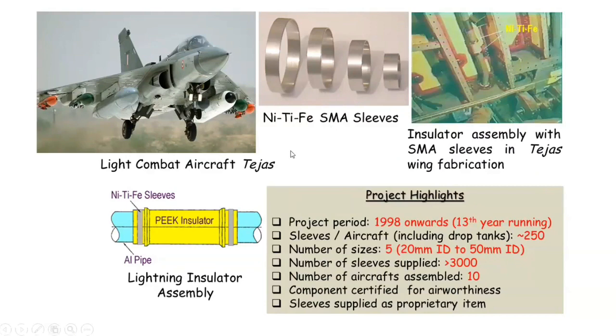So what is done here is that the service window for this application is between -50 and +150 degrees. So this material, which we have got, is 3 atomic % iron in nickel titanium, where the iron goes in place of nickel in the lattice. In this case, the transformation temperature is something like -65. So by about -50, it has recovered its original shape. That means in liquid nitrogen is where we deform it. And when we deploy it and take it out of liquid nitrogen, it will come back to its original shape. And between -50 and +150, it will deliver a constant stress of about 500 MPa, or 70,000 psi, and this will help to put the insulator onto the tubing.